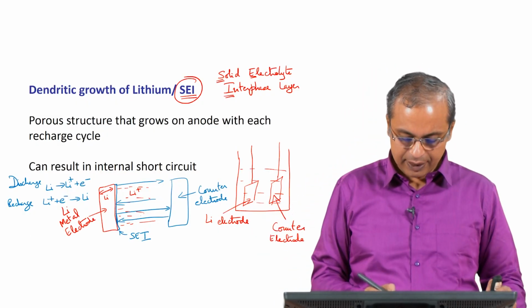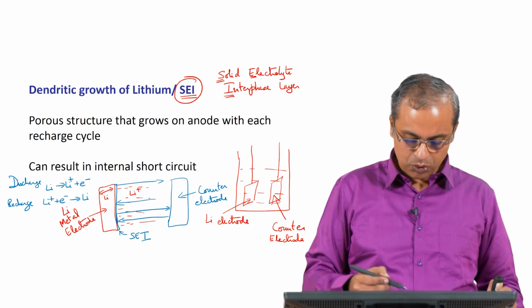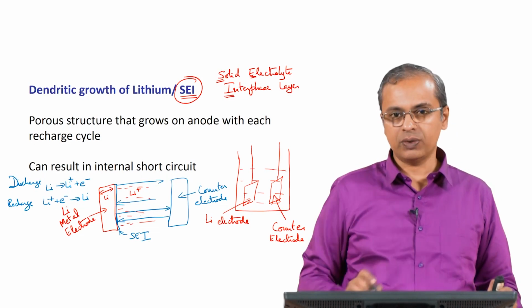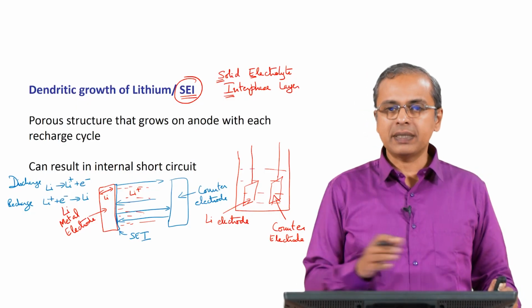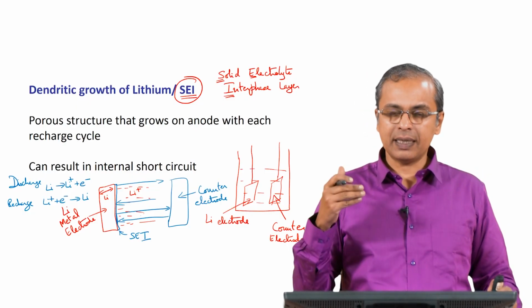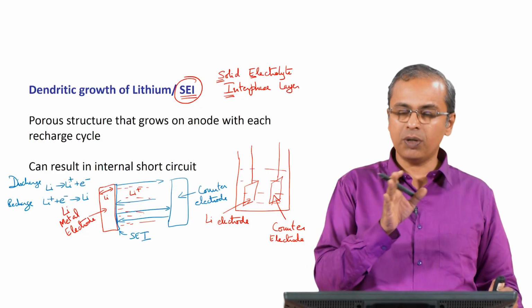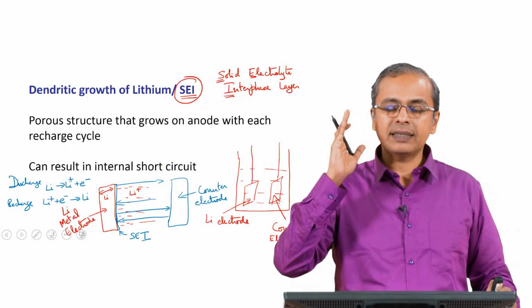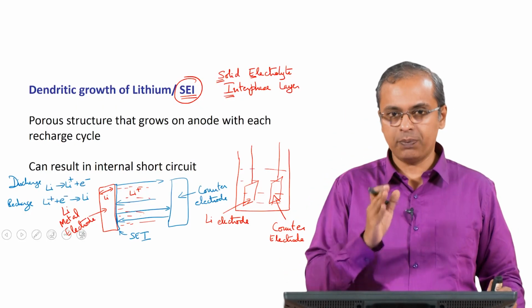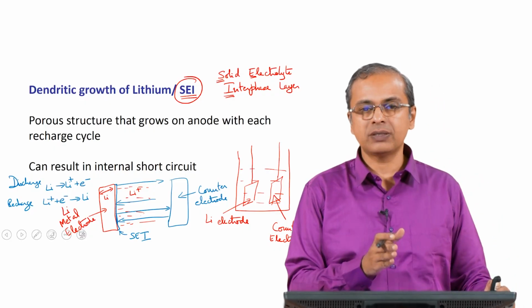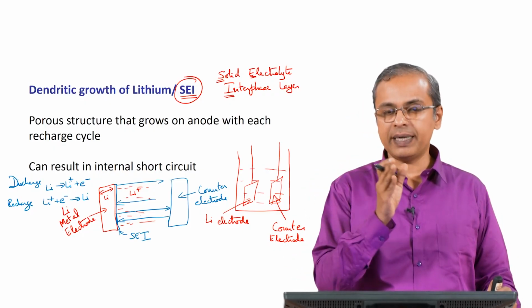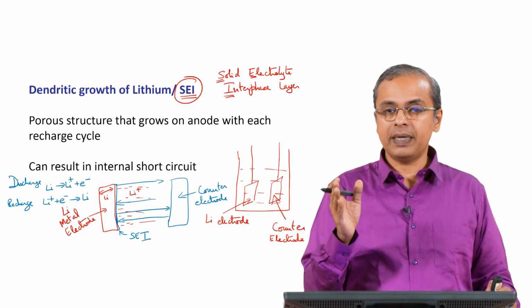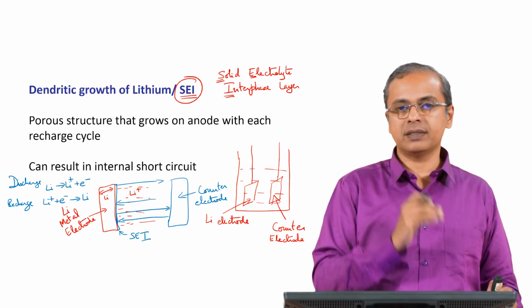Now, for that to happen, the lithium ion has to actually go through this solid electrolyte interface and go back to that metal. When you keep doing this, sometimes it does not go through properly, or it goes in and forms a different kind of structure. It does not plate in a flat manner. That is the problem with this lithium metal. When the lithium ion comes back and plates on the lithium metal, it would be nice if it plated back as a flat structure.